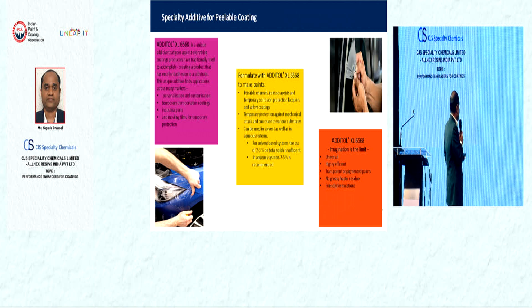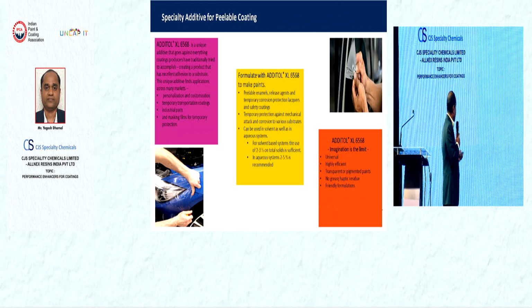On the application side, it is recommended for personalization and customization, then temporary transportation coatings, industrial paints, and masking films for temporary protection. From the formulation point of view, it is universally compatible and can be used in solvent-based as well as water-based systems. For solvent-based, we recommend only 2-3% on total solids, and for waterborne a bit more dosage, that is 2 to 5%. From a product features point of view, it is universal, compatible in solvent-based and water-based. It is highly efficient and can be used in transparent or pigmented paints.